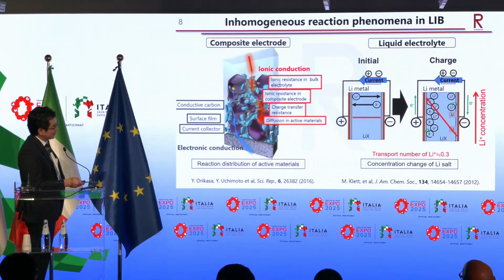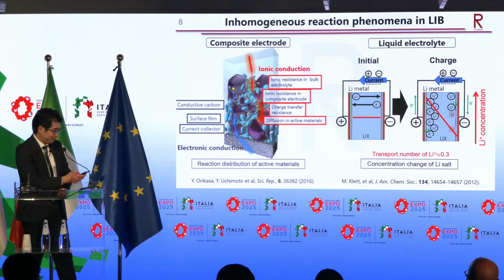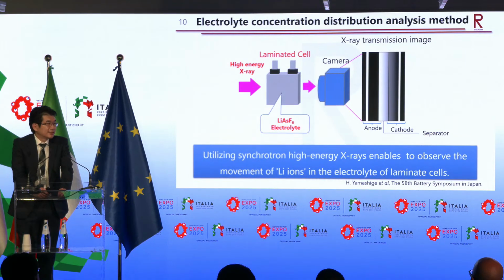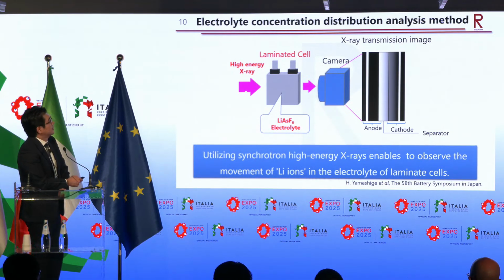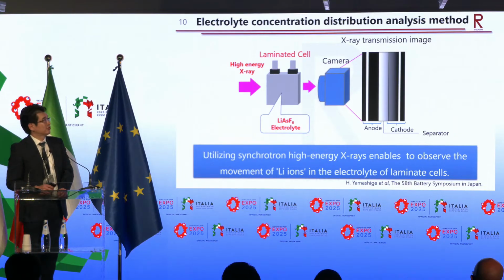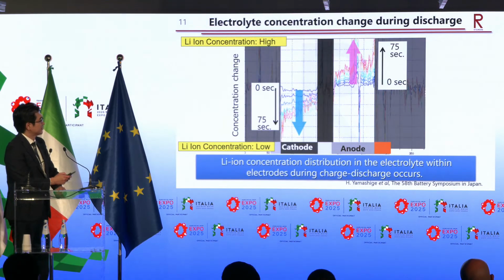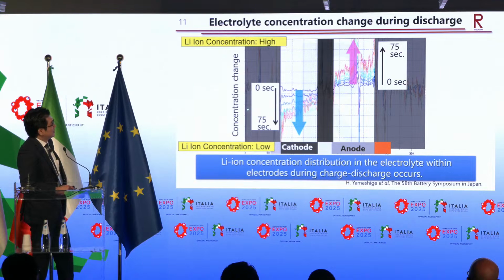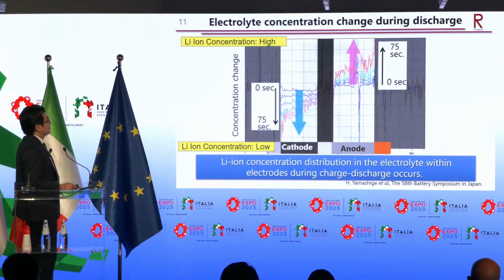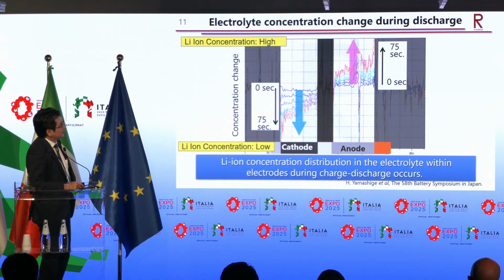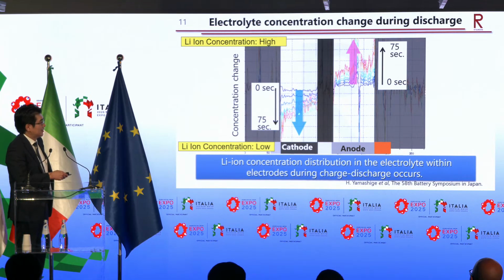So another distribution is electrolyte concentration distribution. To analyze the electrolyte concentration distribution across the electrode and the electrolyte, we use a high-energy X-ray imaging technique. So high-energy X-ray can penetrate the lithium-ion battery cell, so we can directly detect the concentration distribution across the electrode and the electrolyte. So this is the result. The y-axis corresponds to the lithium-ion concentration, and this part is cathode and this part is anode, and the center is electrolyte part. So during charge reaction, the concentration of lithium is increasing on the anode composite electrode. And also the cathode concentration is decreased.